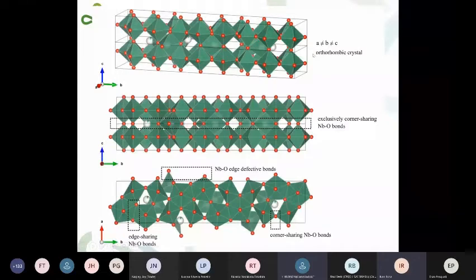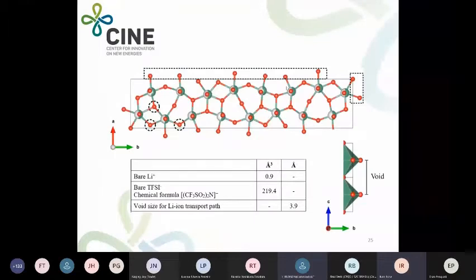With niobium pentoxide, we have this orthorhombic crystal structure, and we have this channel in the middle where the lithium ion could go through it. And it's possible because of these edge defects related to the niobium pentoxide edge defect bonds. So basically, this lithium ion, for example, sodium ion, are very small, on the order of a few angstroms. And the interplanar space from the voids of the niobium pentoxide, for example, is 4 angstrom. I said nanometers, but it's angstrom, okay?